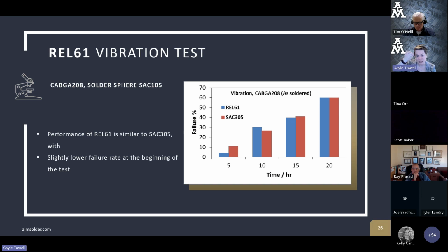This is a vibration test. So here we see, shake it and see if you can break it. And again, REL61's failure rates initially were lower. Later on, they sort of even out though. So in this particular test, we're seeing somewhat comparable results between the REL61 and the SAC305.